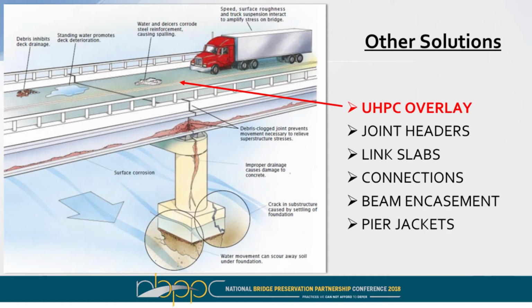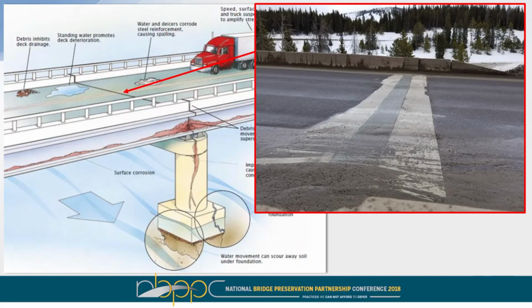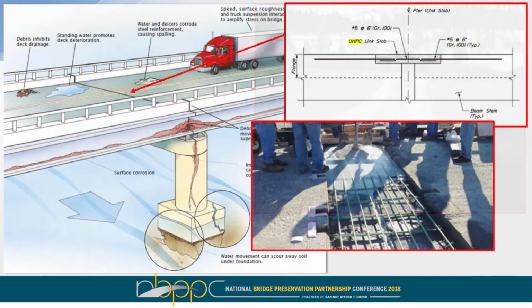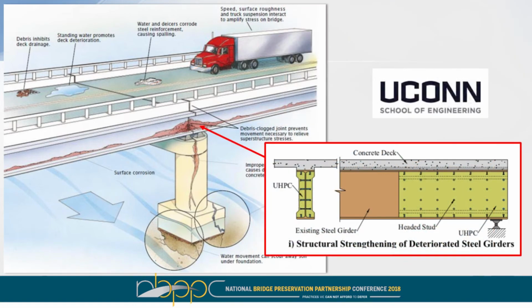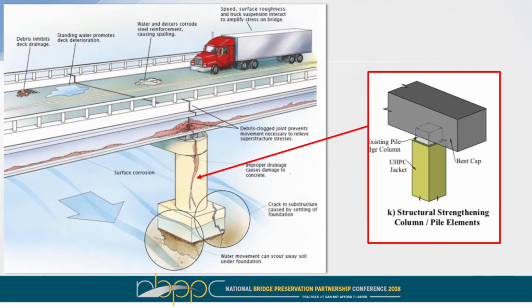Joint headers, link slabs, connections, beam encasements. We did a joint header up in Colorado last year in an area which uses a lot of heavy truck traffic in the winter with chains, and it's held up very well so far. We've done a ton of link slabs in the New York State area, and now Delaware is starting to do some, as well as West Virginia, Maryland. So if you want to eliminate the joint completely, you can put in this flexible linking element to remove that.